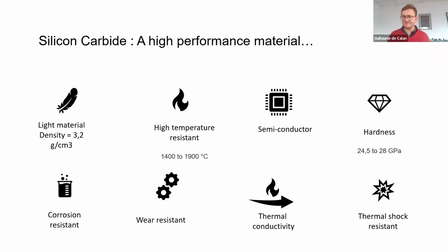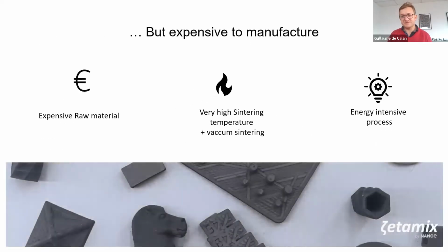You see that there's a lot of attractive properties here, which makes it a material you could think should be everywhere. The reason why it's not everywhere is that it's an expensive material. It's expensive because the raw materials themselves are relatively expensive. They cost a lot of energy to produce. And then the sintering cycles are also extremely expensive because you need very high temperature and vacuum sintering. So the whole process line to make and sinter the material is very energy intensive, and so they cost a lot. At the moment, they particularly cost a lot because energy prices are soaring.